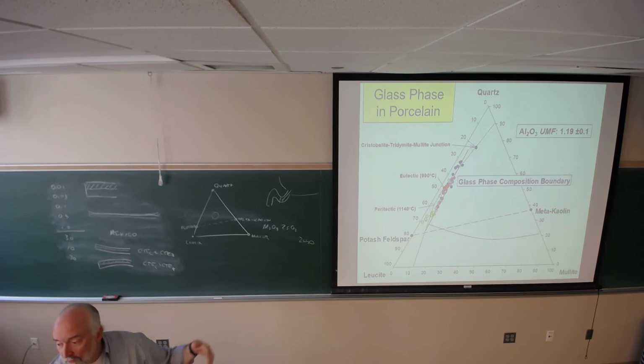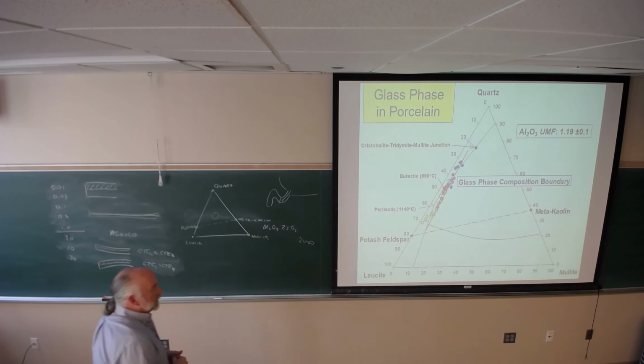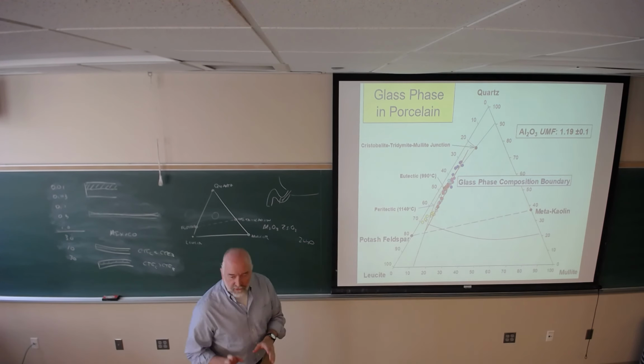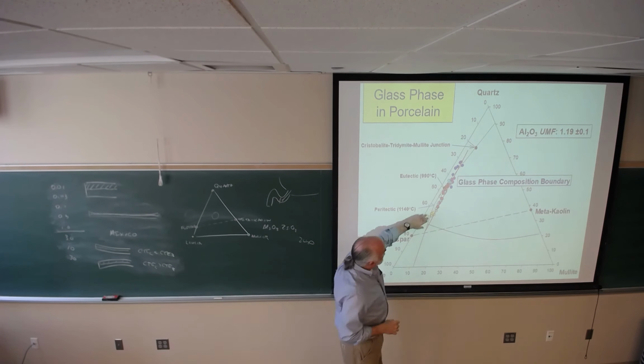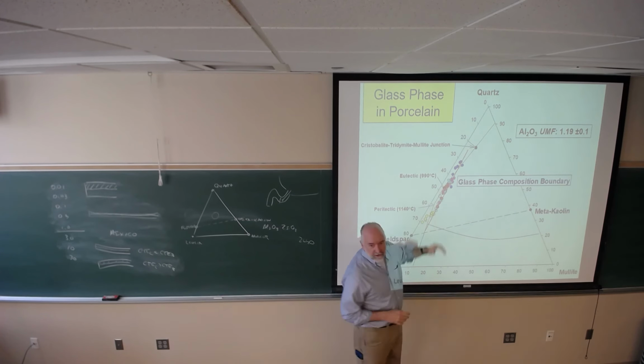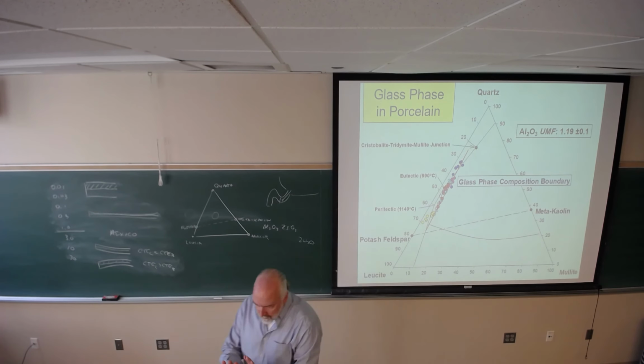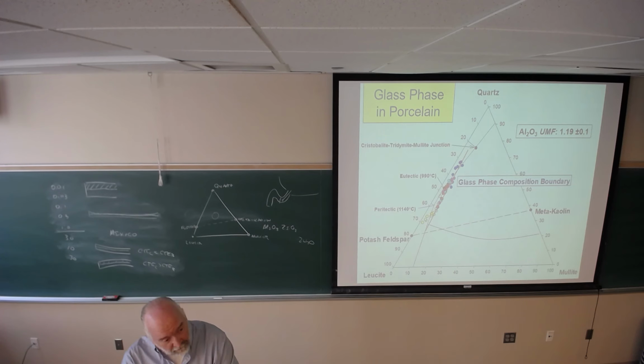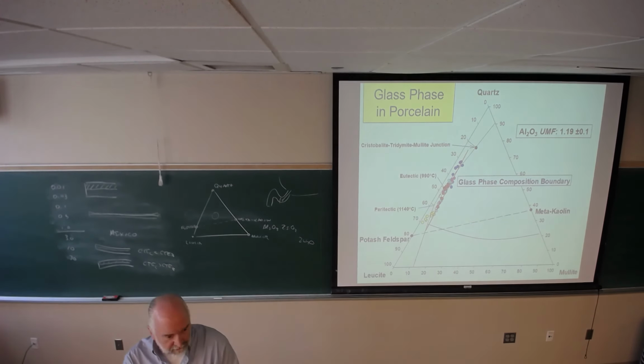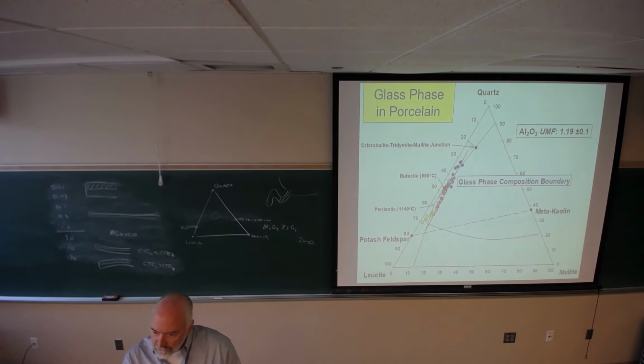mole of flux. And then what happens is as we change temperature or change quartz particle size to a very limited extent, if I go up in temperature, I dissolve more silicon in the glass. But that ratio of alkali, in fact, alkali plus alkaline earth, if I have calcium or magnesium in the porcelain, which is relatively rare, to alumina stays fixed.